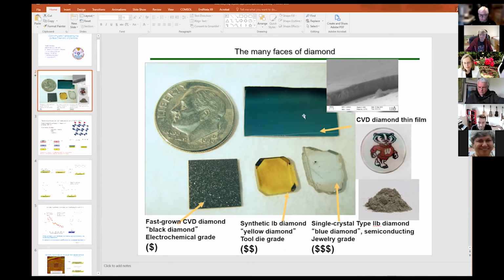This work is done for 111 oriented diamond, right? If you would use 001 oriented diamond, what changes in the results would you expect? That's a good question. I'm positive we used this diamond, which is a nice 111 sample. I'm almost positive we did the same thing with 100. This is a 100 diamond, as well as diamond thin films. And what we've been able to see, there's very little difference in the reactivity corresponding to the different crystal faces.